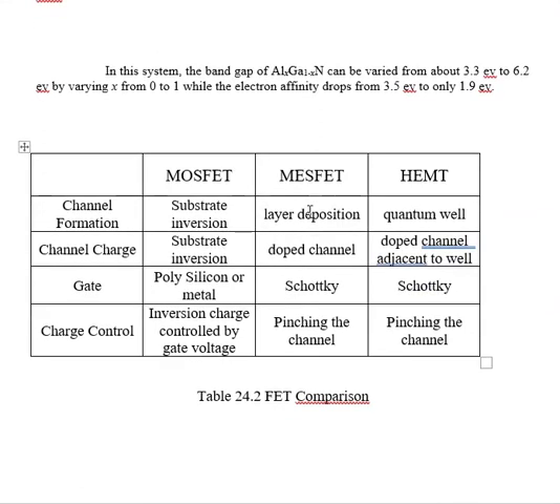Now let's look at a general comparison of the MOSFET versus MESFET versus HEMT. These are general considerations. The channel formation in the MOSFET is through substrate inversion. In the MESFET, we have a channel deposition, which is very expensive. In the HEMT, we form a quantum well by putting two materials together, a high band gap material next to a lower band gap material. The channel charge in the MOSFET is due to inversion. In the MESFET, the deposited layer is doped, and in the HEMT, the high band gap material is heavily doped.